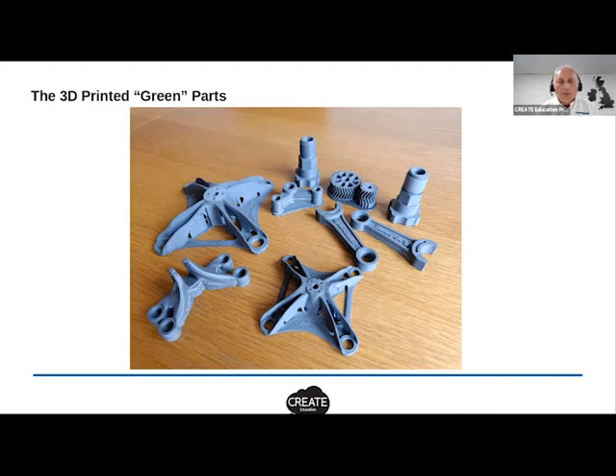These parts shrink when you go through the next stage, which is debind and sintering, which is effectively post-processing these 3D printed parts into the finished metal part. And as the part shrinks, you want the support material to shrink at the same rate. So the support material needs to be the same material as the model. This isn't like an option where you could use a soluble support. It needs to be the same metal that you're printing the main part with, because it needs to shrink at the same rate. But you need to ensure that those support materials don't fuse themselves to the model. And the white ceramic support material is there to create that barrier and interface that stops that fusing from taking place, and means that the support will be able to be removed from the part once it's finished.